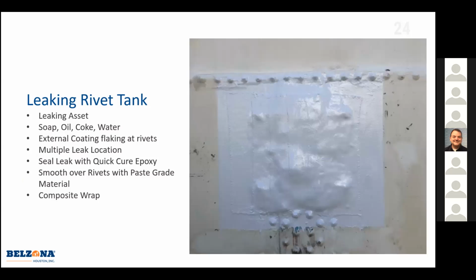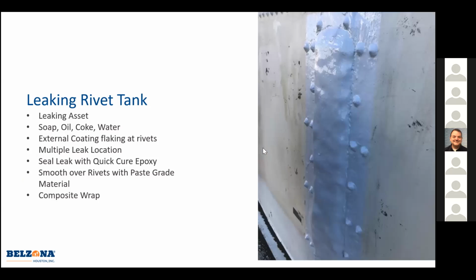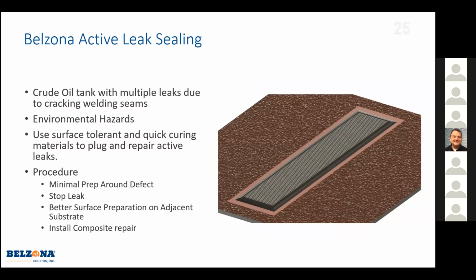And this is what it came out to look like for a lot of them. The rivets and the bolts do come out a little bit bulky because you do have to pack over those bolts at times. So that's why you see this lump here, just covering up the bolts. But this was done across 4 or 5 of their tanks, and each tank had about 6 to 10 locations where it was leaking, and they would attack about one location a day.